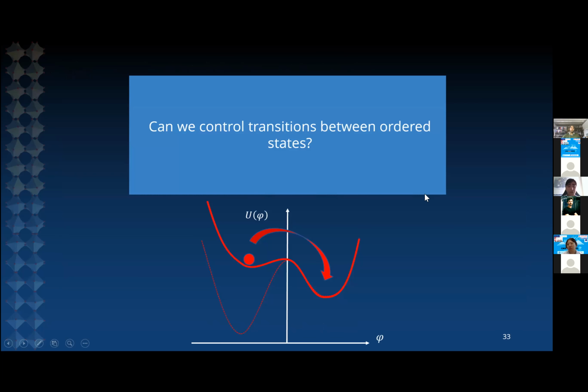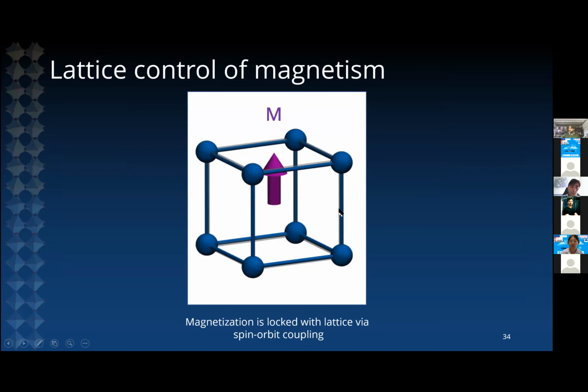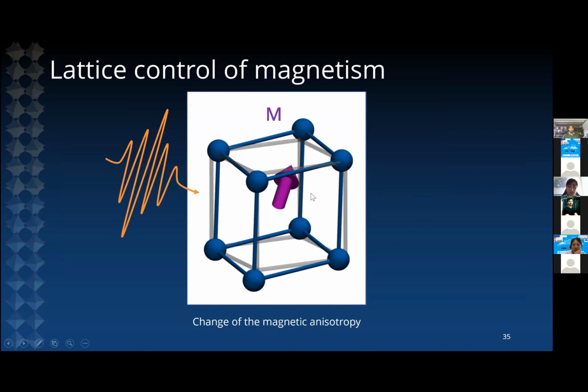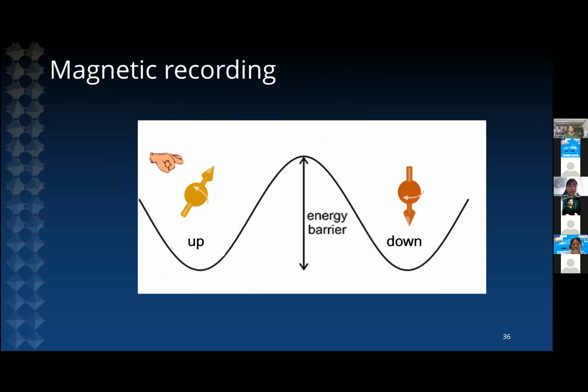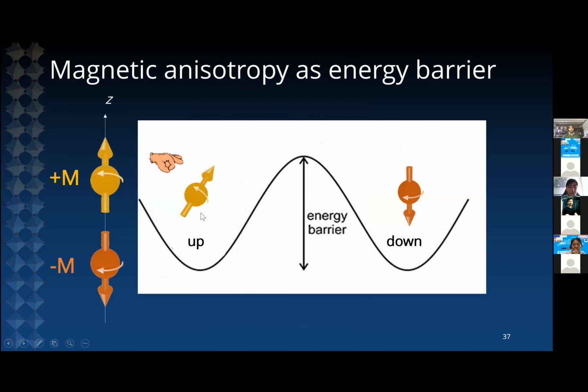So now the interesting question is, instead of just melting antiferromagnetic order, can we control a transition between order states or states of matter? So we know that magnetization is locked to the crystal lattice via spin-orbit coupling. And if we manipulate the crystal lattice, we can generate a change in magnetic anisotropy, and therefore a reorientation of the magnetization. And this is relevant to the problem of magnetic recording, since the magnetic anisotropy controls the energy barrier between an up state and a down state in a magnetic material.